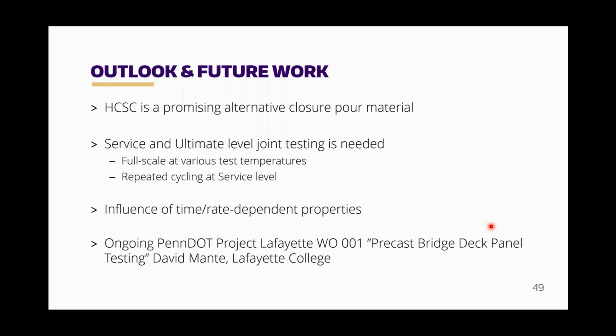The influence of the time and rate dependent properties, so this is thinking about creep, and also the fact that the dynamic modulus for polymer concretes is quite a bit higher than the static modulus. And so that's something that is important to consider as well. It also, in addition to everything we talked about today, has some rate dependent properties as well. And I just wanted to point out that there's an ongoing PennDOT project being done by David Mante at Lafayette College, who is building some more of these precast deck panel specimens with HCSC closure pours. And so hopefully we'll get some more results from that shortly.